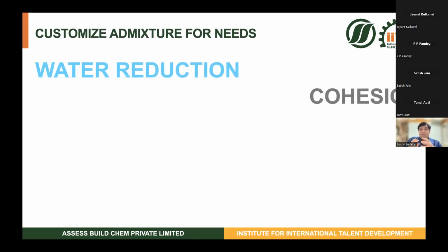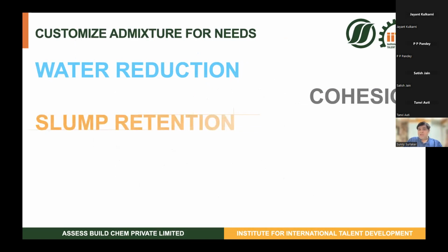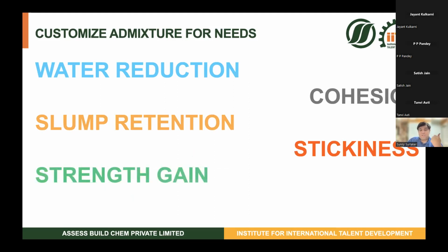But with this kind of a mix, the problem in Virar is the availability of sand. What you get is what the local guys give you. And this kind of sand sometimes is very rich in fines, at other times it's very deficient in fines. So we had to design an admixture which could maintain the cohesion, at the same time maintain slump and reduce stickiness, because this kind of sand really had the tendency to clump the entire concrete mix together.